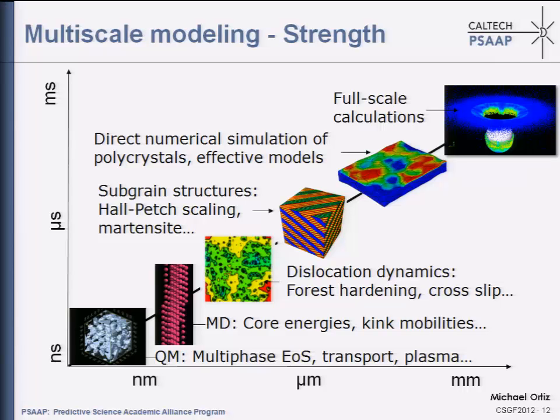Typically you develop very fine subgrain structures, that I'll come back to in a second. Then if you keep looking down in the length scales and time scales, you begin to see individual defects, so dislocations, vacancies, and so on. Of course these are mediated very directly by the atomistic structure of the material, but still are at a continuum length scale. Maybe the scale of microns or hundreds of nanometers is still within the purview of continuum models. And then if you look at individual defects, here you see the atomistic structure of matter, and you look at individual dislocations, you may see the core structure of each one of these dislocations, which, as you know, are line defects in crystals.